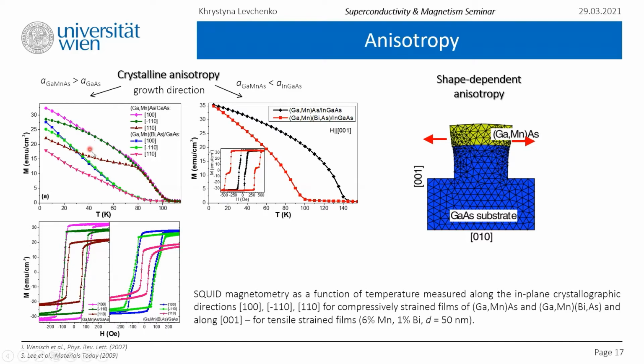If we look at the magnitude as a function of the temperature, we may derive the holy grail of all the magnetic measurements, which is the Curie temperature. The Curie temperature is where the curve flattens. The measurements were conducted along the three easy directions, and they all come to one line in the end. For ternary compounds, the Curie temperature is around 110 kelvins, while for quaternary compounds, it's more like between 90 and 100 kelvins. The temperature was enhanced for the samples grown on indium gallium arsenide, though, with 140 for ternary and 100 kelvins for quaternary compounds.